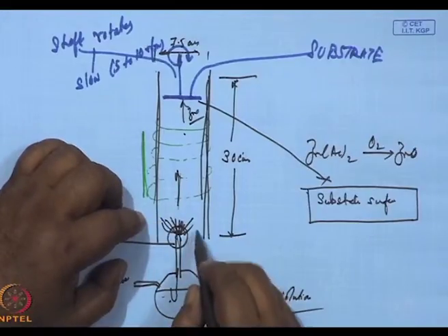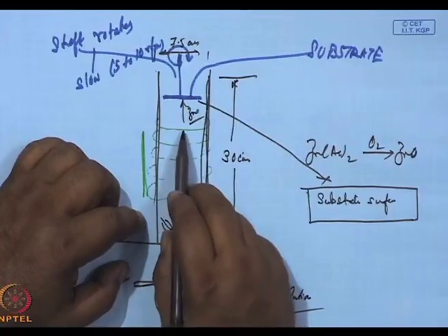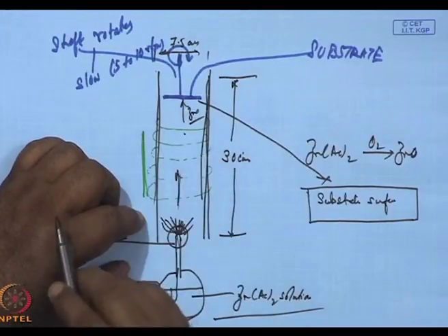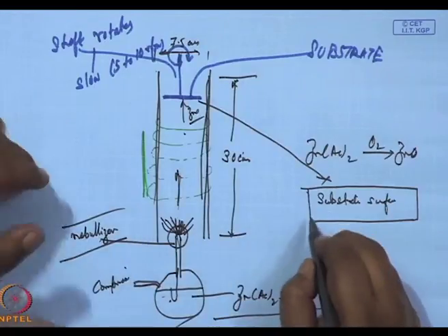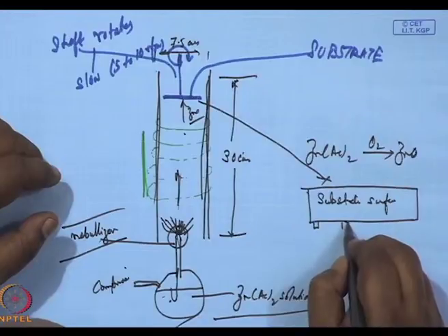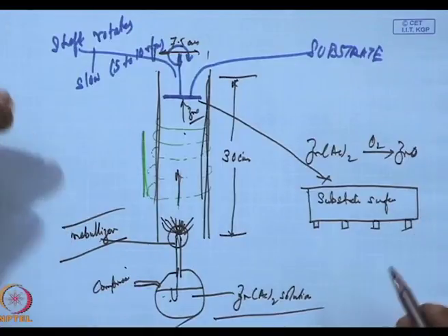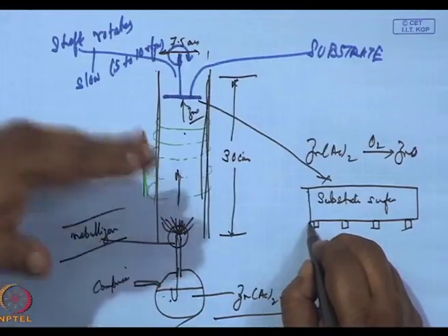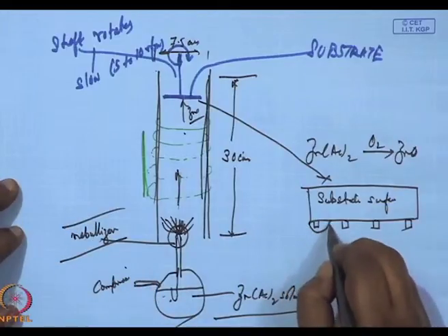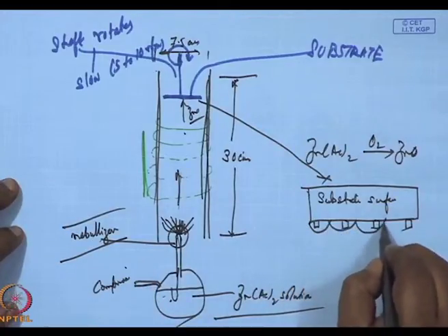The reason why I picked zinc acetate was that zinc acetate burns very cleanly. It does not leave behind a carbon residue. So here, this zinc acetate mist will travel through this hot zone up and hit this surface. With time, first we may have a few random deposits depending on the nucleation area. Then as more zinc oxide evaporates, they keep building up thicker and thicker layers.